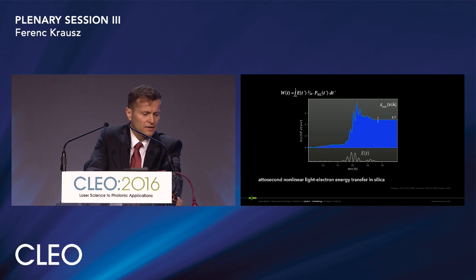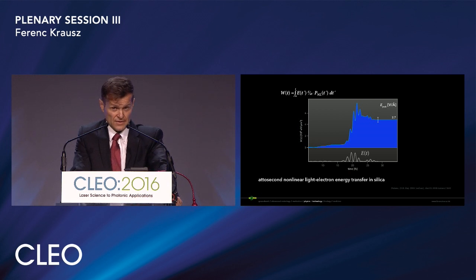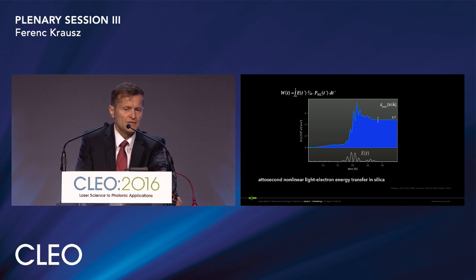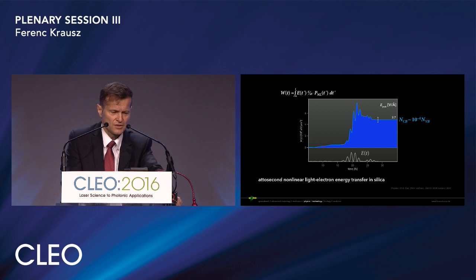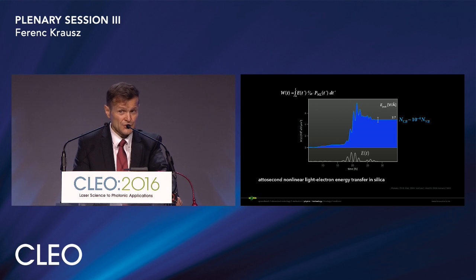Near breakdown at a peak electric field strength of 2.7 volt per angstrom, a substantial, actually even dominant fraction of the transferred energy is irreversible by the field. This irreversible energy transfer is related to a multiphoton-induced conduction band population that is evaluated as a tiny fraction of the density of valence band electrons. The fraction is actually so small that this conduction band population is hardly measurable by any other means. In spite of its low value, this strong field-induced conduction band population is really crucially important